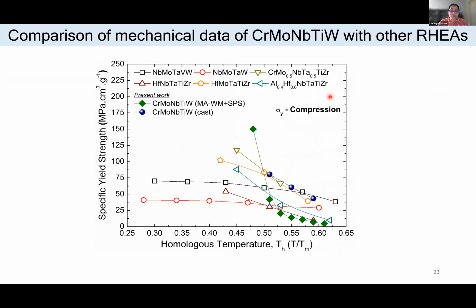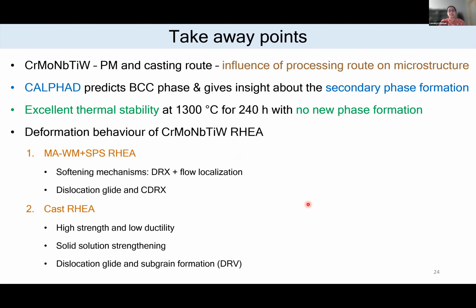So now to compare the behavior of these alloys with other HEAs, I have tried to plot the yield strength variation. As we can see, the cast alloy is on par with the other cast alloys. Whereas this mechanically alloyed and sintered alloy has a very high strength at 0.5 of homologous temperature, but it decreases as we go to high temperature. But we can say that this composition, when we make it through arc melting, is on par with the literature.